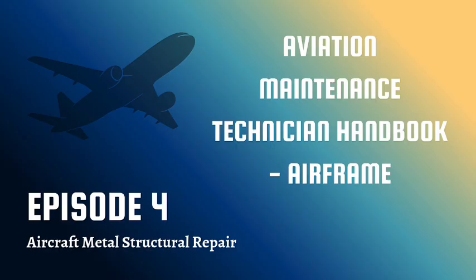Right. Critical. After drilling, there are always burrs left around the edge. Removing them seems important. Non-negotiable. Burrs must be removed. You can use a deburring tool, a scraper, or even just carefully rotate a larger drill bit by hand in the hole. Why are burrs such a problem? Several reasons. They prevent the parts from fitting tightly together, no flat surface contact. They can scratch the protective coating off the rivet shank as it's inserted, inviting corrosion. And maybe worst of all, burrs trapped between sheets create tiny gaps. These gaps allow movement, fretting, and trap moisture, leading to corrosion and potential fatigue failure right there in the joint.